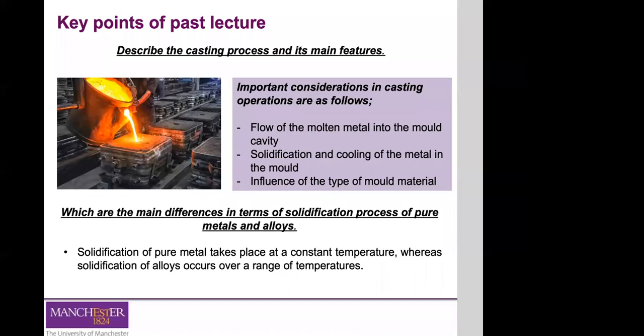The main factors affecting the solidification of metals and the cool down of the material until it reaches ambient temperature include: the type of metal — there are differences between pure metals and alloys; the thermal properties of the metal and the moulds, which directly influence the temperature exchange during solidification and the final properties of the parts; and the geometrical relationship between the volume and surface area of the casting, which plays an important role in the solidification process. The shape of the moulds is also significant.